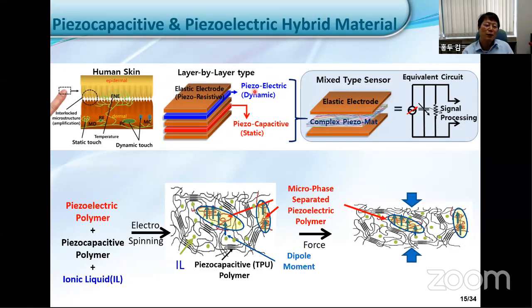So if you think about real application, especially two-dimensional application, you have a lot of electrodes, and that also requires a many-wire system. So instead of this layer-by-layer structure, we try to make one polymer system, which I call a complex piezo material. Then, using just a two-electrode system, we can detect both piezoelectric and piezocapacitance signals, if we can have a proper hybrid material. So we think about it this way.